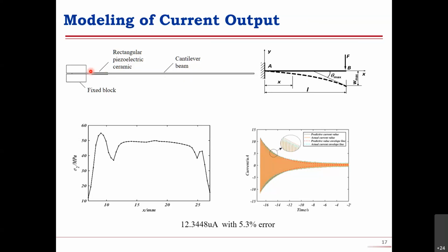So we sum these different current sources, and we can get the total current output. And we compared our experiment with our simulation. We found that they fit well with each other.